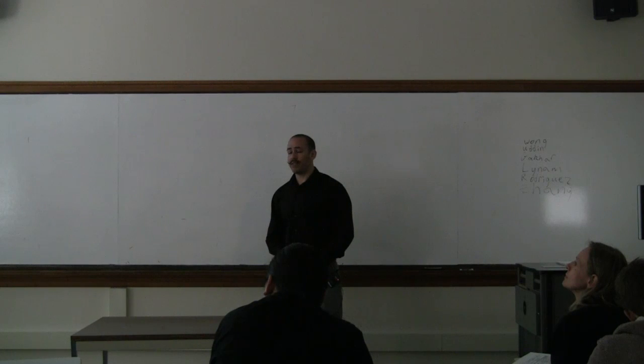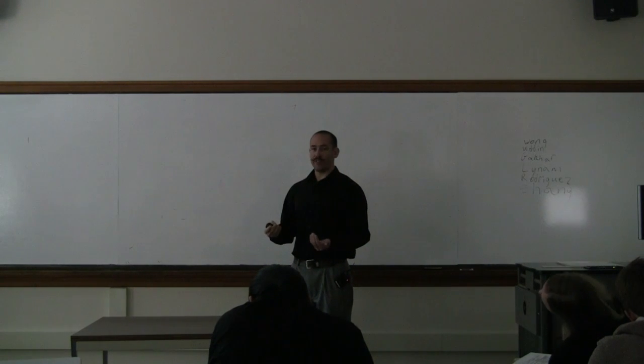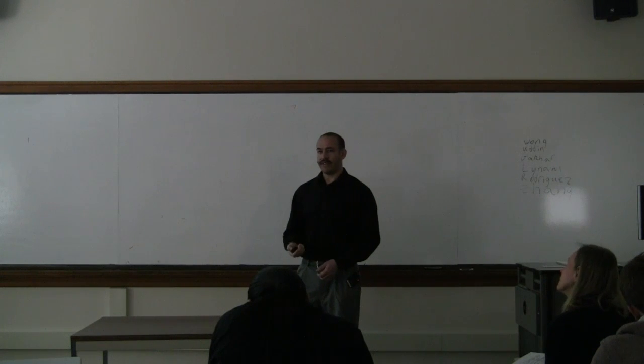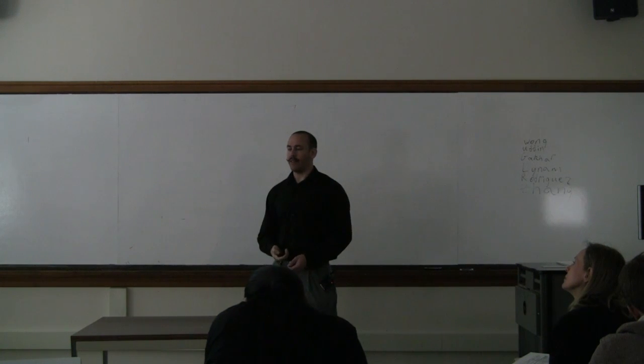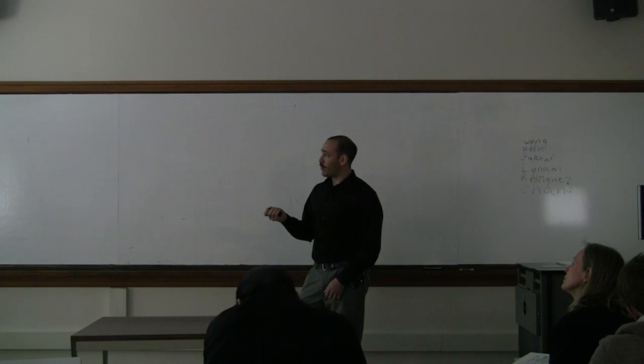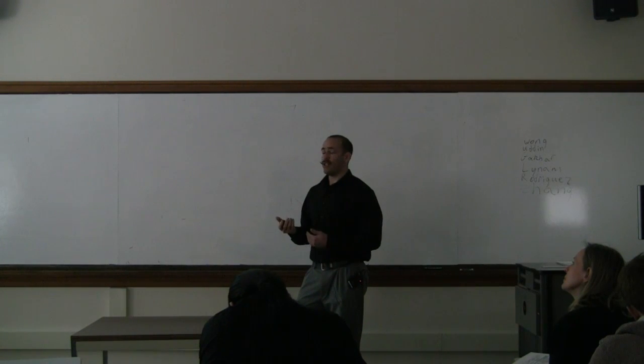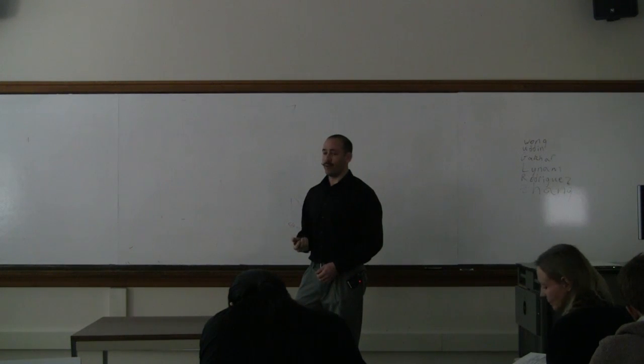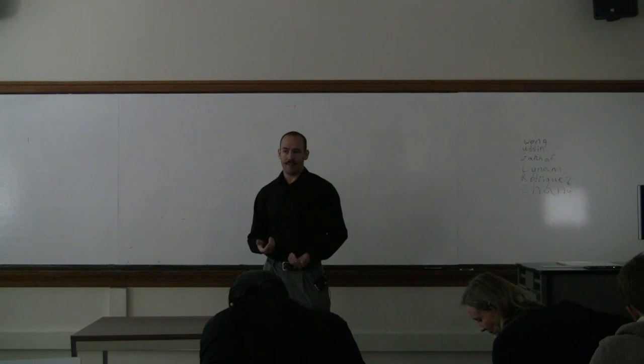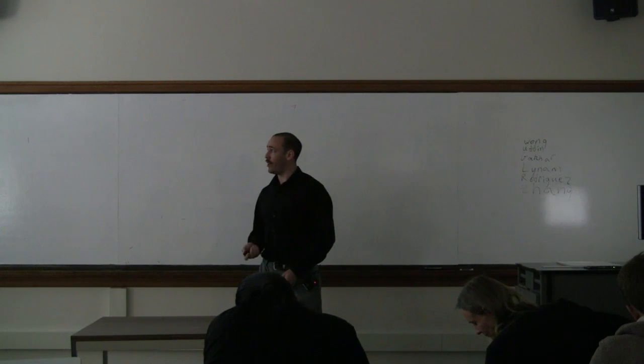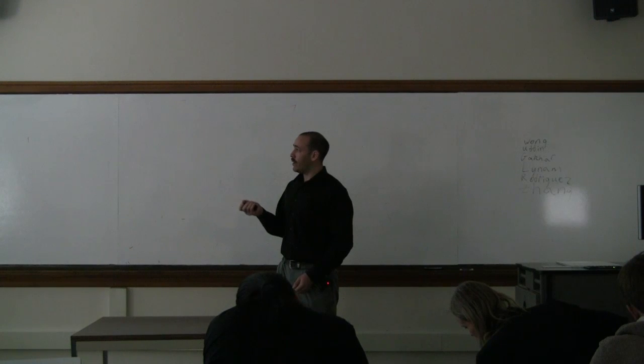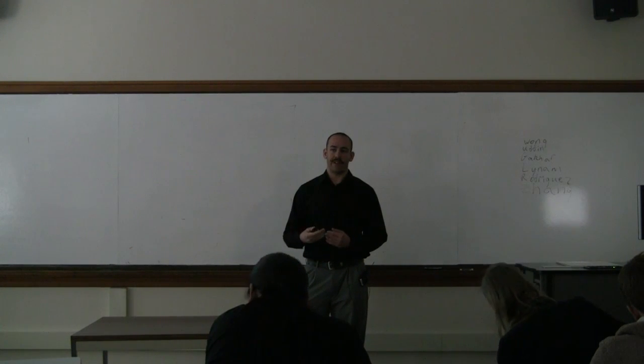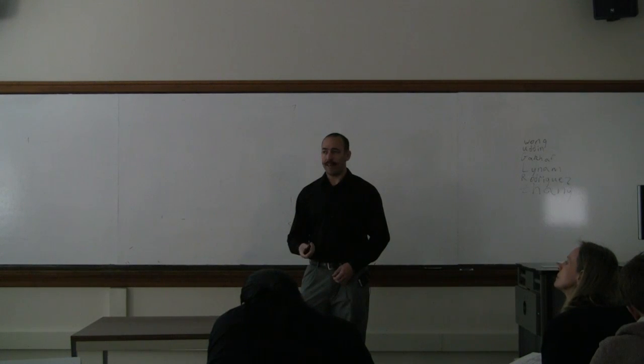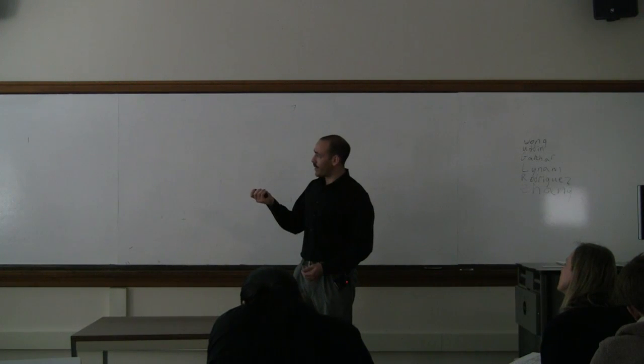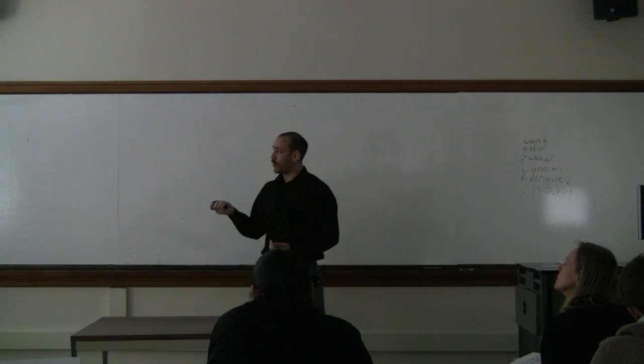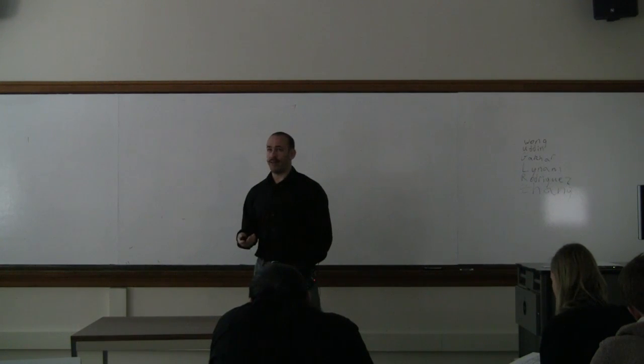Okay, Raman spectroscopy results. Now, the important thing to realize is we want to actually have the chemistry of the coating characterized to see if we have a model similar to that of the chromate conversion coating. And here we have multiple peaks that show where the molybdenum has formed. We do have Mo double bonds and stretching modes that show that molybdate has in fact formed on the surface of the aluminum alloy. Here we have the sodium molybdate curve. This is one of the components in the coating bath, and we have one peak that matches up, but the reason it doesn't match up for the other two is